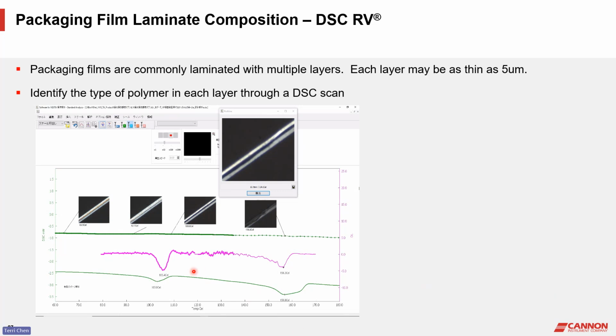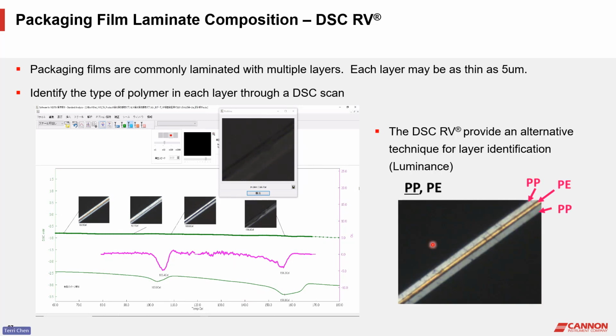Then, as we further increase the temperature, when the temperature rises to 150 and 160 degrees C, which is the melting temperature of polypropylene, the 2 outer layers both turn black. So from this combination of testing results, we can conclude that this particular packaging film is made of 3 layers. The center layer is made of polyethylene and the 2 outer layers are polypropylene.